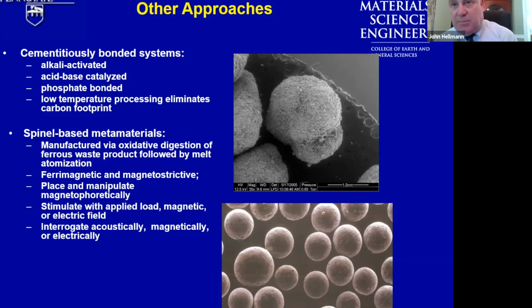Similarly, we're looking at other byproducts of industrial processes for proppant applications. One is the swarf that's left over from the manufacturing of ferrous-based ball bearings. The swarf, or grinding powders, if you will, can be transformed back to ceramic using a flame atomization approach, which forms first wustite, which is highly fluid, and spheritizes in the flame due to surface tension, and then later in the flame plume, by adjusting oxygen partial pressure, can be converted to magnetite.